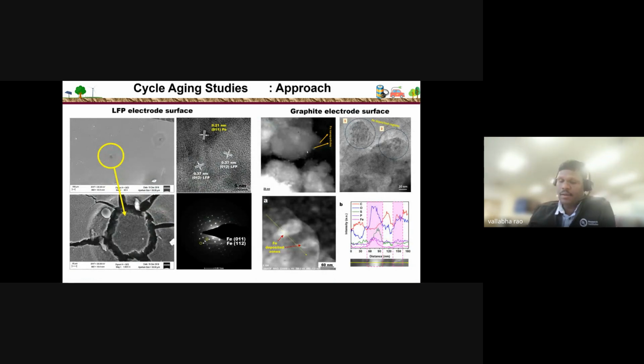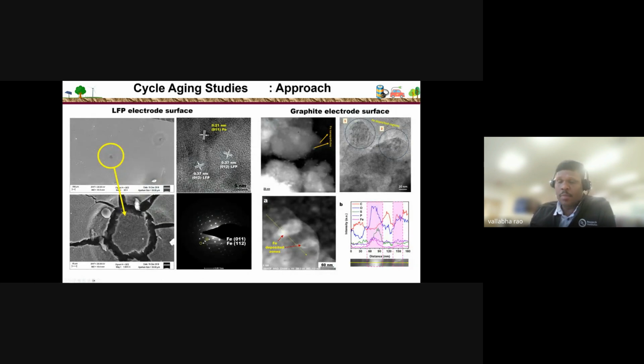To further understand the 100 SOC, 100 DOD test conditions, we have carried out microscopy analysis of both the cathode and anode surfaces. Interestingly, the cathode surfaces have a lot of cracks, and we can see the electrolyte wettability is also very low. Where these cracks were formed, that area is where the cathode electrode degradation occurred, and then that degraded material dissolved in the electrolyte and deposited on the opposite side of the electrode.